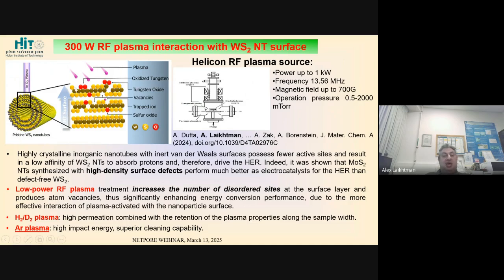It turned out that because of plasma, we have very minor oxidation of the first layers, nearly between the pores of the initial layers of the nanotubes. You can see here the schematic of the process. And in this way, using the plasma, we induce high-density surface defects, and then they perform much better as electrocatalysts than defect-free WS2. Defect-free WS2 means the WS2 nanoparticles before plasma treatment.